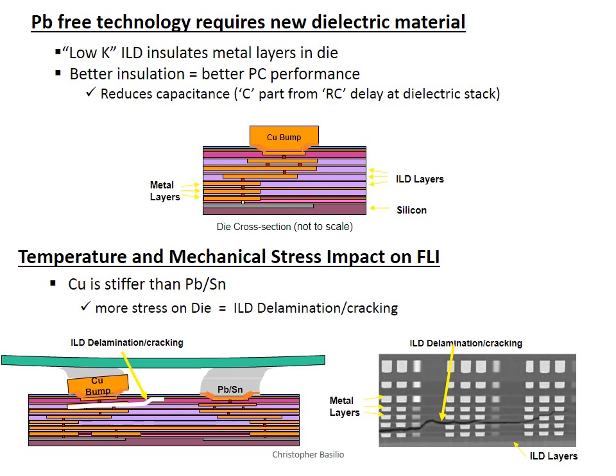The intrinsically high mechanical stiffness of lead-free solder creates additional stress to the die, causing ILD delamination and cracking. The lead-free solder high melting point is another concern, as it increases the CTE mismatch between the die and the substrate. The CTE mismatch causes tremendous stress on the FLI and the ILD underneath, which ultimately leads to ILD delamination and cracking. The image on the left shows the mechanism behind the ILD delamination, while the image on the right shows a typical ILD delam cracking on a lead-free interconnect device.